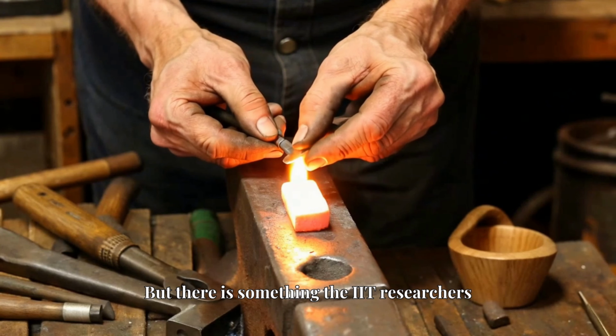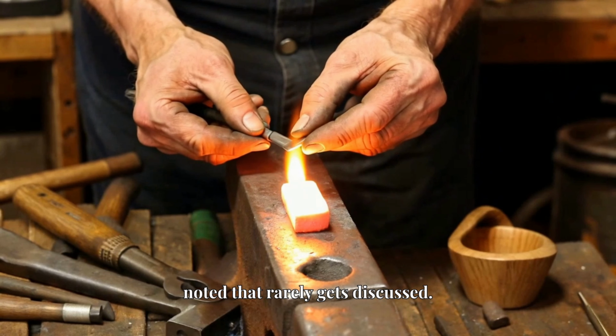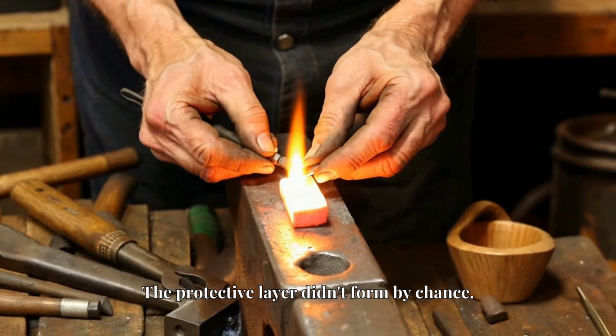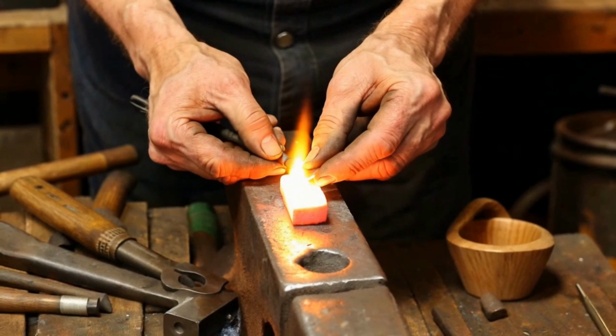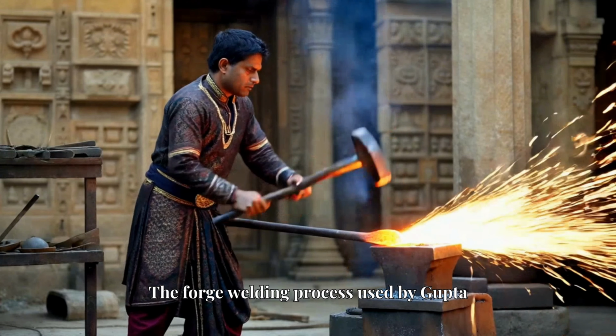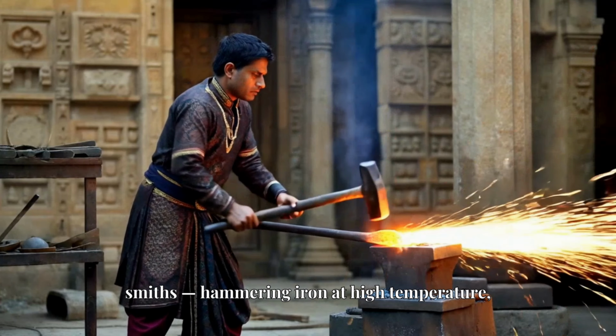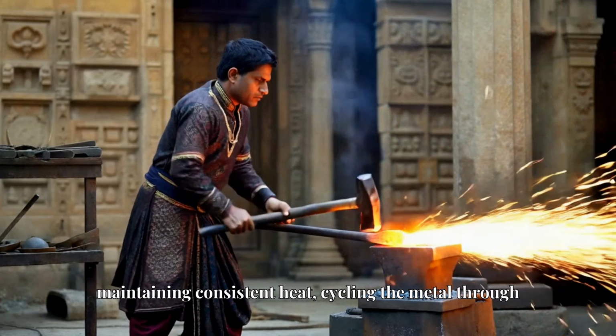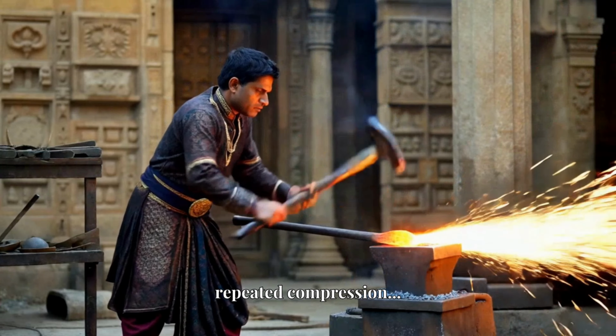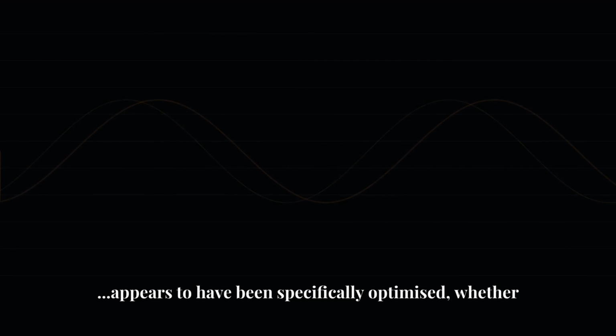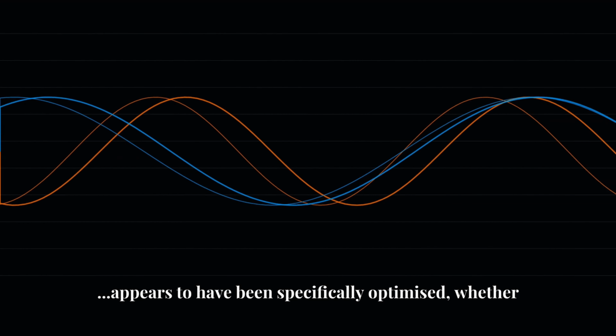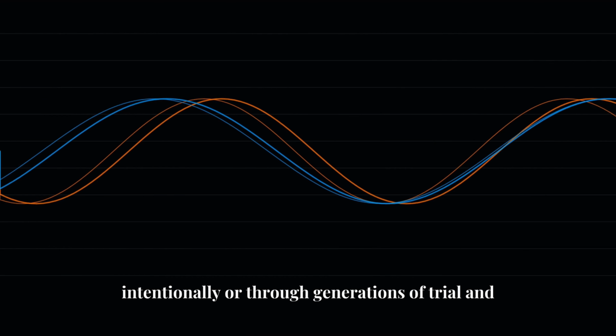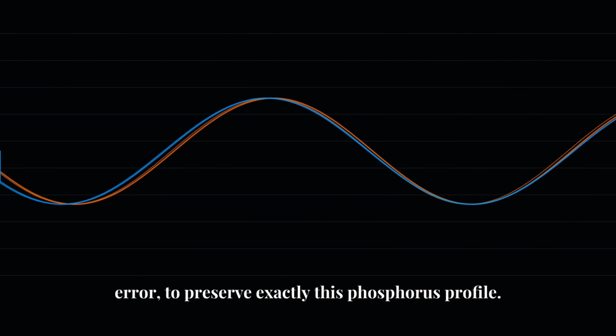But there is something the IIT researchers noted that rarely gets discussed. The protective layer didn't form by chance. The forge welding process used by Gupta smiths, hammering iron at high temperature, maintaining consistent heat, cycling the metal through repeated compression, appears to have been specifically optimized, whether intentionally or through generations of trial and error, to preserve exactly this phosphorus profile.